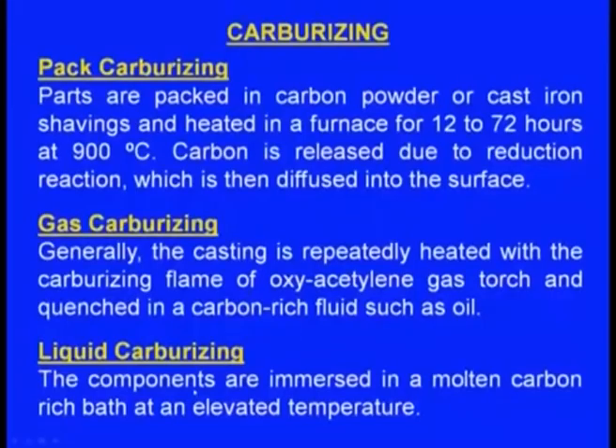Next one, liquid carburizing. What is this? The components are immersed in a molten carbon rich bath at an elevated temperature, right. So there will be a bath which contains molten carbon at an elevated temperature and the component will be immersed in that bath. Then the carbon from this carbon rich bath will diffuse into the surface of the casting and the surface will be hardened. So carburizing is for hardening the surface of the casting, maybe the entire surface or a part of the surface.